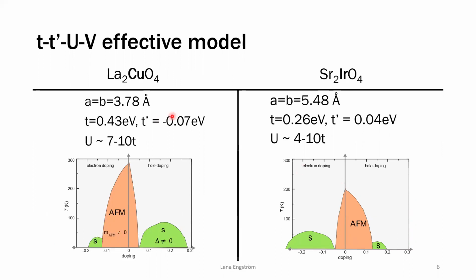Where the difference with the minus sign here is that you have flipped electron doping and hole doping, and due to having an energy scale that is basically halved, you get that the orders only persist to about half the energy. But from this simple comparison, you can just say this material should be superconducting. And the first problem with this, among many, is that we know that this prediction only is valid for electron doping because we do have more bands on the hole doping side here.